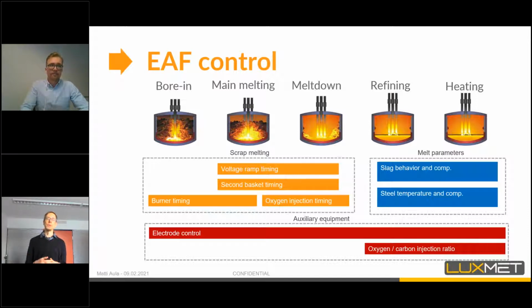On the other hand, if you use a multiple basket charge, in practice, when the scrap is melting down, you would like to insert the second or third basket. You want to do this as soon as it fits safely, because then you can make sure that the electricity efficiency is maximal. And then when the scrap has molten, there are flat bath conditions. In these conditions, many factories making carbon steels utilize oxygen injections to foam the slag. In this phase, it's important to control the amount of oxygen to carbon, so that we get as much energy as possible out of the carbon, but still don't over-oxidize the slag.